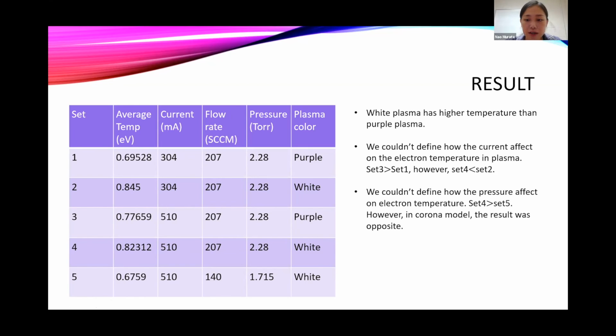Also, we couldn't define how the pressure affect on electron temperature. In this result from Boltzmann plot method, set 4, which has high pressure, has higher temperature than set 5. However, in the corona model, the result was opposite. Set 5 has higher temperature than set 4.